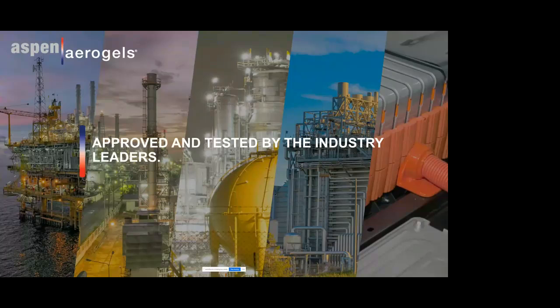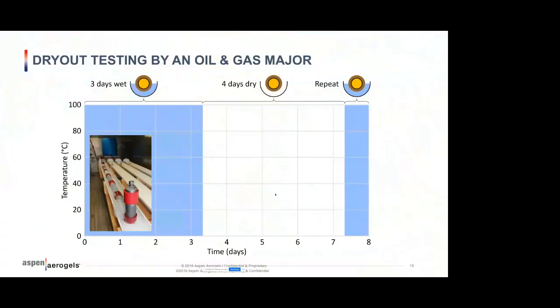So I'm going to talk to you about some of the testing that we've done in the industry. The first testing I'm going to talk about was done by Exxon, and this is a test where they were looking at the moisture uptake of the insulation. They tested two different types of insulation, Pyrogel against traditional mineral wool. They had these half pipes, which you can see with the red sections insulated with different products, and they filled the half pipe with water for 3 days, left it dry for 4 days, and repeated this process for 8 days whilst heating the pipe to an 80-degree cycle as well.